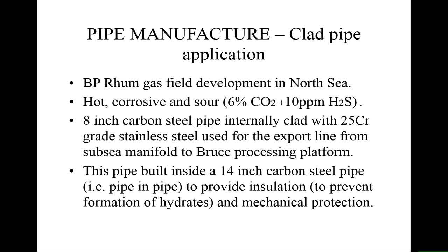Now the interesting part about this also was that 8-inch pipe was built into a 14-inch carbon steel pipe, so we had a very complicated pipe within a pipe construction, and that's because there were worries about forming hydrates, methane hydrates in the system. So the pipe was an insulator for temperature, and it actually had some umbilicals going down there with electronics and heaters and things. So the pipe itself that was laid was not just the delivery pipe, it was the complete pipe necessary to do all the things that had to happen in that effectively riser situation.